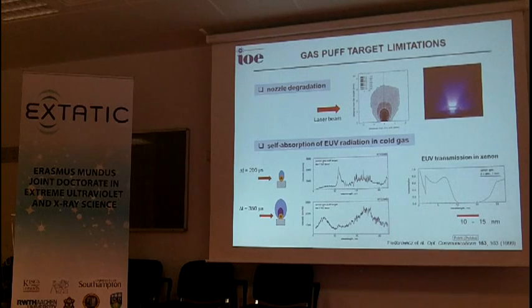However, during this research, we found that this simple arrangement, I mean gas puff target, is good, but not so good. It's good for single shot, for short operation time. After some time, because in this experiment we could work with repetition rate up to 10 Hertz, we observe a degradation of the nozzle because of the direction of the plasma.